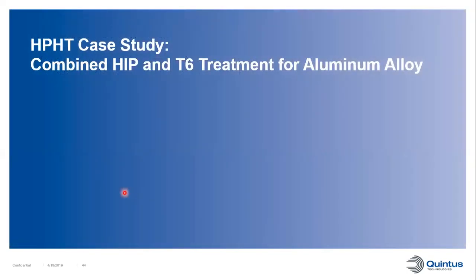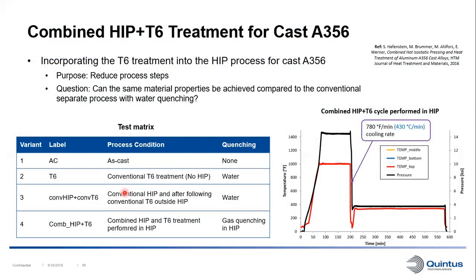Another case study here is for a combined HIP and T6 treatment, an age hardening for an aluminum alloy. And this study was done together with the Technical University of Munich in Germany. Here we wanted to see if we could incorporate the T6 treatment into the HIP process for a cast A356 material. And the purpose of this is to reduce process steps in your process chain. And the question is if we could achieve the same material properties with heat treatment in HIP compared to a conventional heat treatment with water quenching.